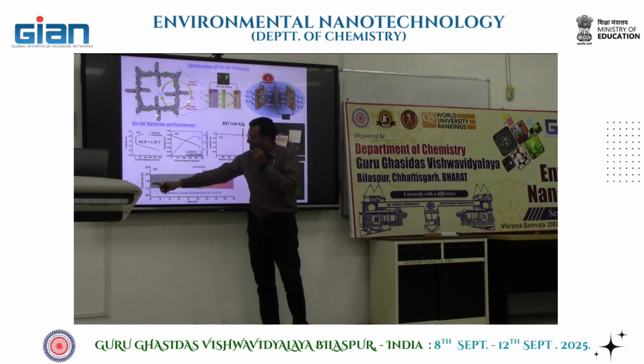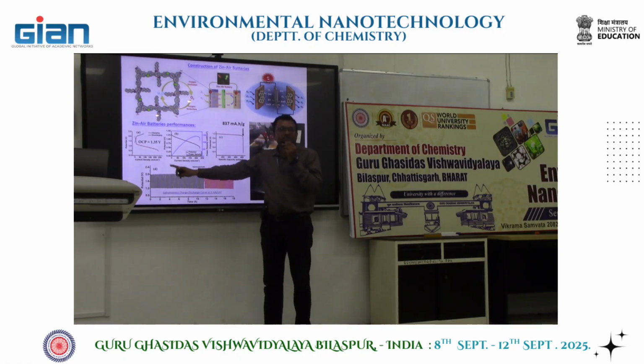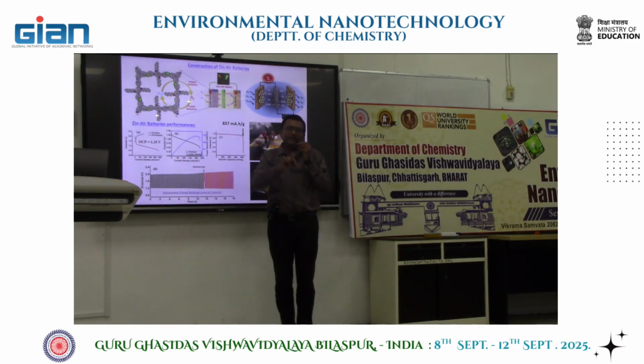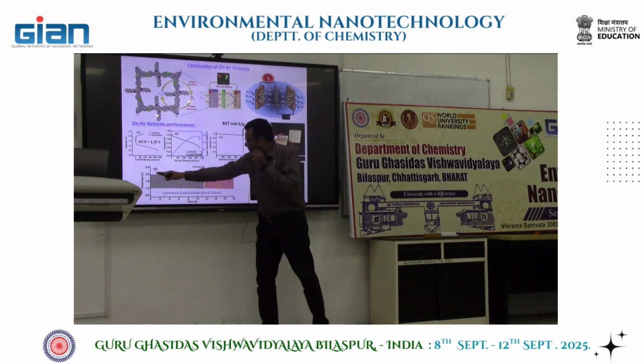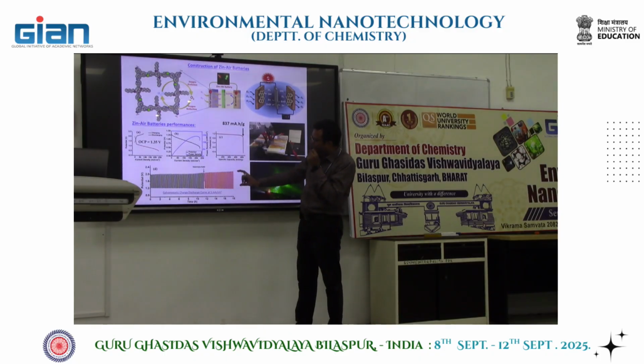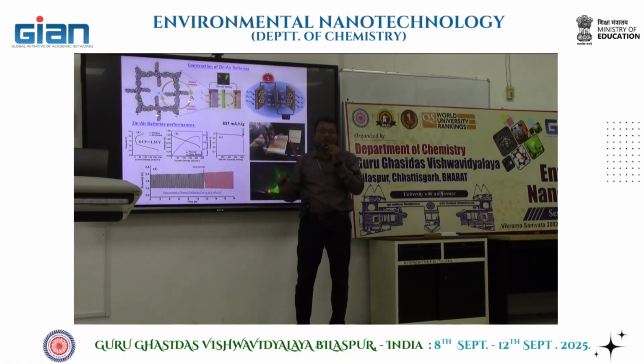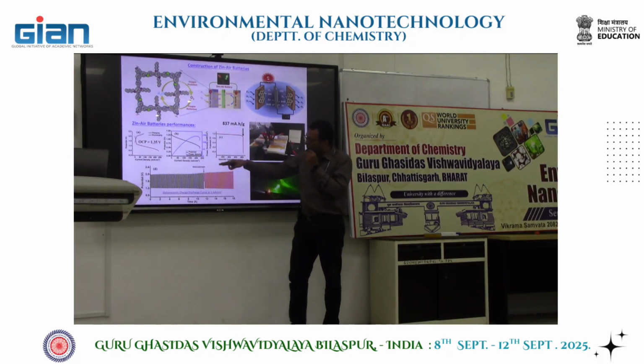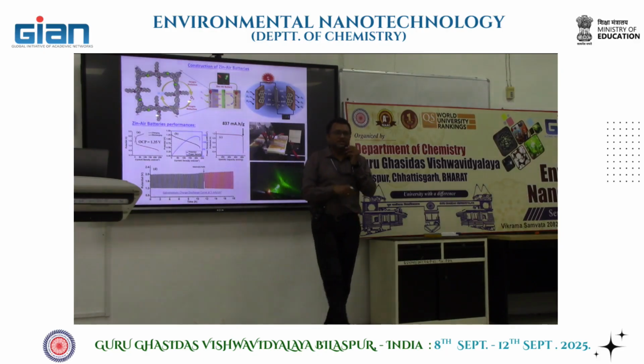So basically one side it is charging, another side it is discharging, and that represents directly ORR and OER reactions. Although at the end of 18 hours the graph remains broader and it is taking much more time compared to earlier, it is still within the range of charging and discharging.